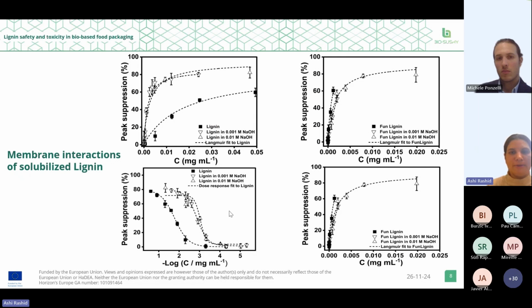In the bottom plots, the data is fitted to the conventional dose response models, where the interactions increase with the amount of dose of the lignin. And again, we got good fits.